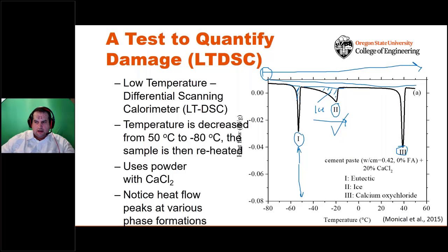The third thing that happens is we get this peak over here, which is our calcium oxychloride. And what you'll notice is this happens at higher temperatures. Turns out this peak moves around depending upon the concentration of the salt. Low concentrations were over here. High concentrations were right about here.